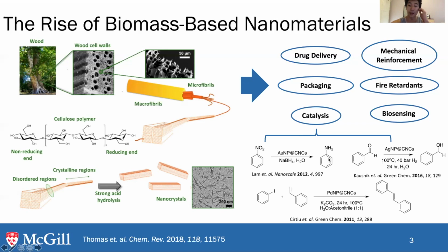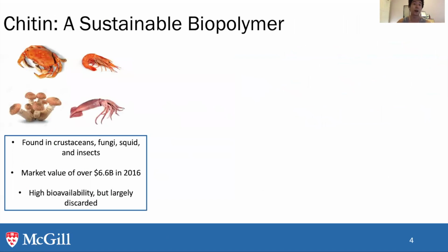This highlights our recent work using these for a variety of organic transformations. What we do is put metal nanoparticles onto the cellulose nanocrystals such that we can immobilize them and use them for a longer period of time. Another biopolymer that's less looked at than cellulose is chitin. It's found within shells of crustaceans such as crab and shrimp, as well as some squid, as well as fungi. It has very high bioavailability, with a market value of over 6.6 billion.